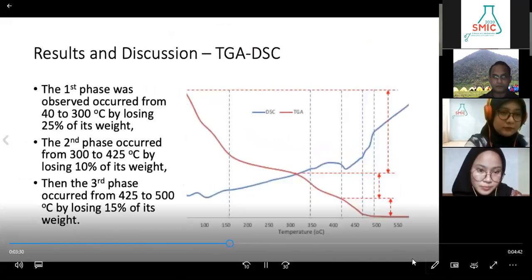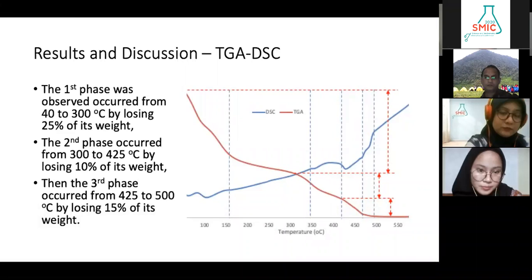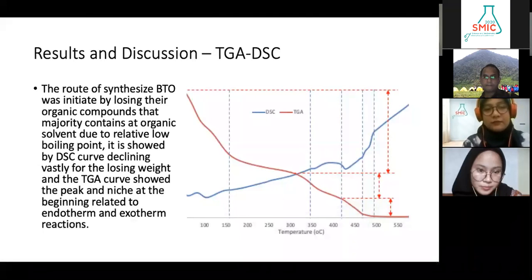And for the results and discussion, the first is TGA and DSC. In general, we separate it into 3 phases. The first is from 40 to 300 degrees, losing 25% of its weight. The second phase occurred at 300 to 425 degrees Celsius, losing 10% of its weight. Then the third phase occurred from 425 to 500 degrees Celsius, losing 15% of its weight. The synthesis of BTO was initiated by losing organic compounds because they have a lower boiling point. It is shown by the DSC curve declining fast for weight loss.